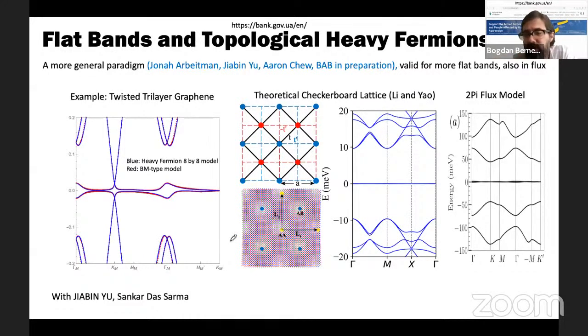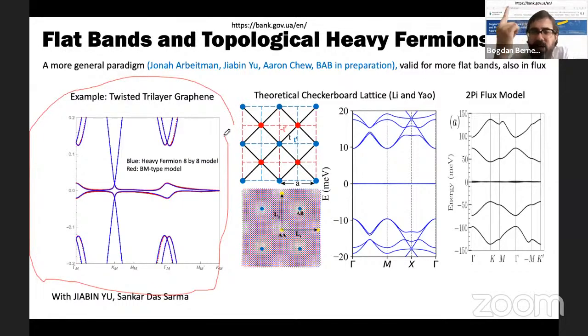But now with the heavy fermion model, you have a very simple model which turns out to match the band structure of twisted trilayer graphene, even in electric field. This is the extra thing that they have in twisted trilayer graphene: they can apply an electric field, a displacement field, and now change things. The interesting thing is the appearance of an extra Dirac, high velocity Dirac fermion at one of the K Moiré points.